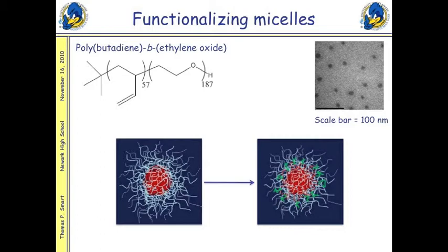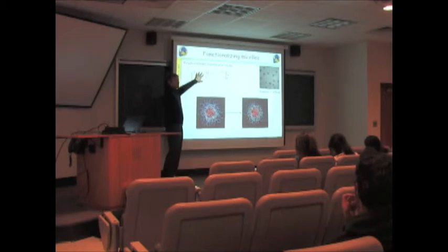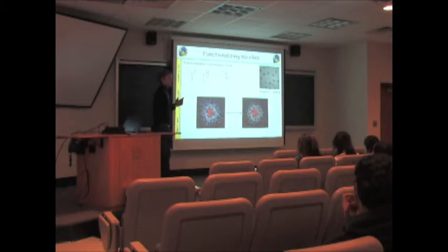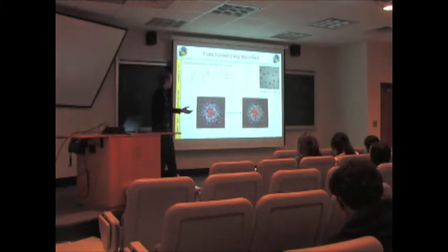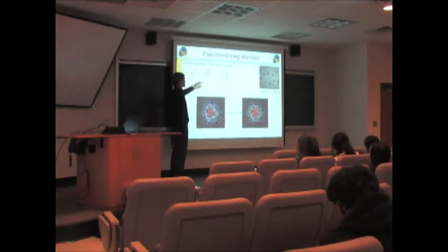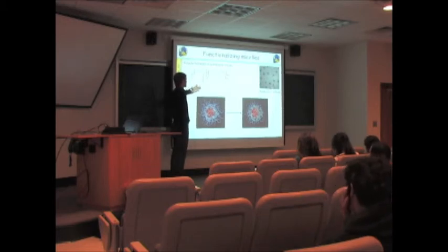If you were to make this portion of the polymer responsive to a change in pH, then when that was released inside the cell, say a drop in pH would add, if you had an amine group, so a nitrogen on the end, you could protonate this, it would become charged.